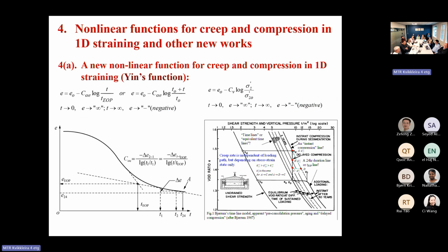I won't go into details. One more thing is also related to the bearing, and you can see the curve. On the high stress, actually, the curves are not really parallel. They are getting close. You can see here, getting close. Of course, on the small stress range they are parallel, not too bad. For example, here at very high pressure, the curves will converge. It's not linear because the void ratio at most reaches zero. So if we use a log function, void ratio can go to infinity, or even go negative. This is compression.